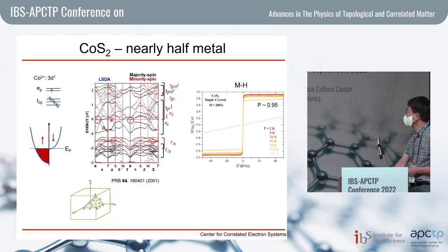almost empty. Indeed, band calculation shows that the minority eg band is almost empty, just slightly touches the Fermi level. Meanwhile, the majority spin in black is mostly occupied. So if we measure